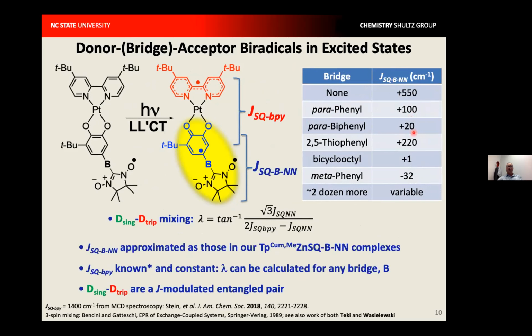Biphenyl takes it down to 20, a thiophene bridge plus 220. No pi system, just using bicyclooctyl, takes the coupling down to 1 reciprocal centimeter, and we can even change the sign of the exchange coupling by going from para-phenylene to meta-phenylene and make the singlet of the zinc complex the ground state, which reverses D-trip and quartet in the excited state of the platinum complexes.